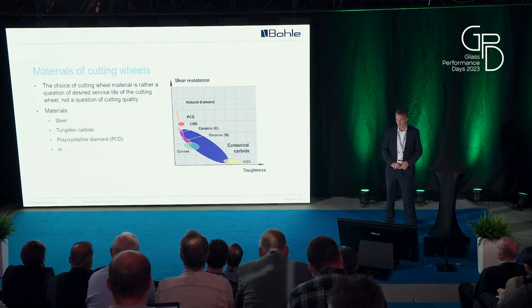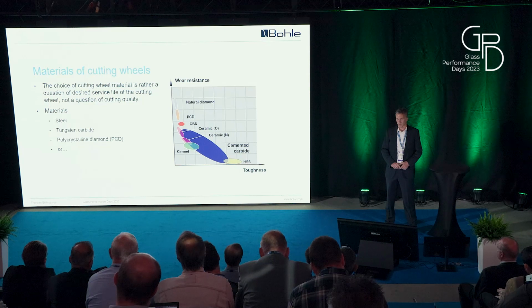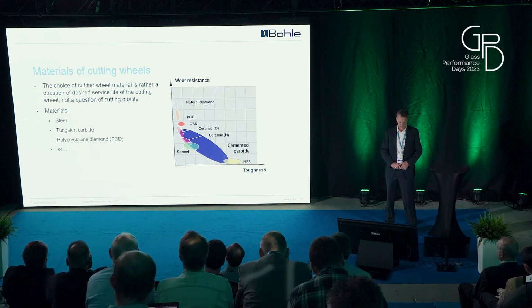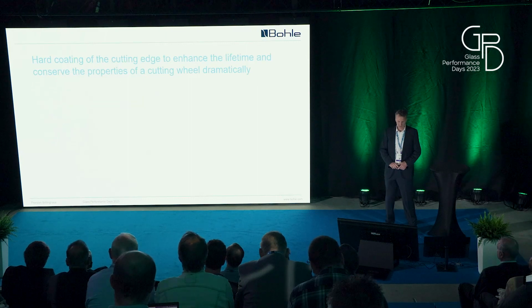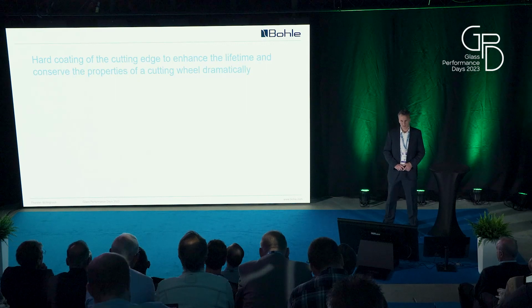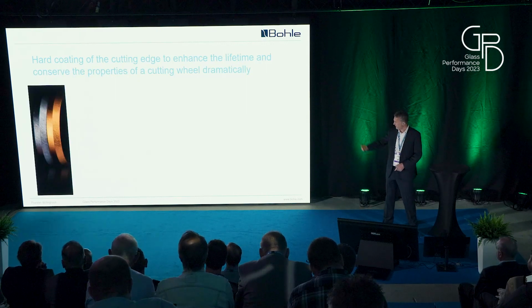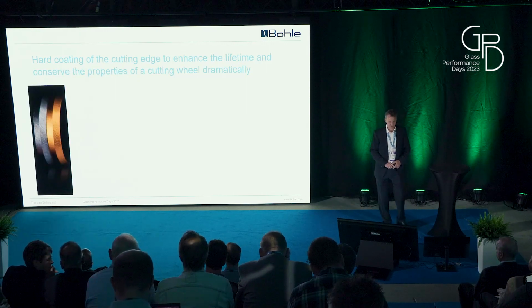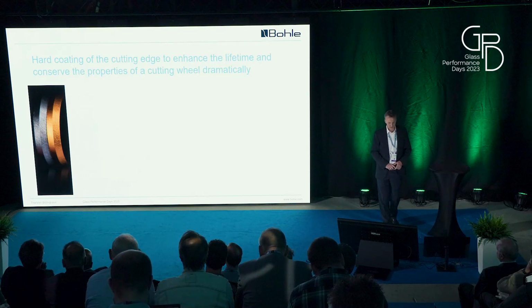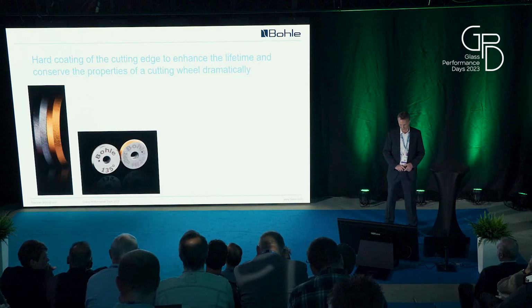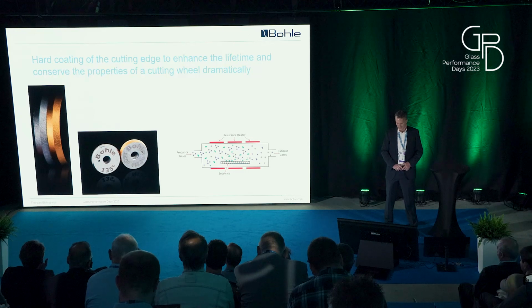So one idea was, how can a compromise be found between the two? And the idea is that you have a hard coating on the cutting edge to enhance lifetime and conserve the properties of the wheel. On the left side of the picture, you see a classic cutting wheel, and just beside it a hard-coated cutting wheel, which is done via some gas phase process.